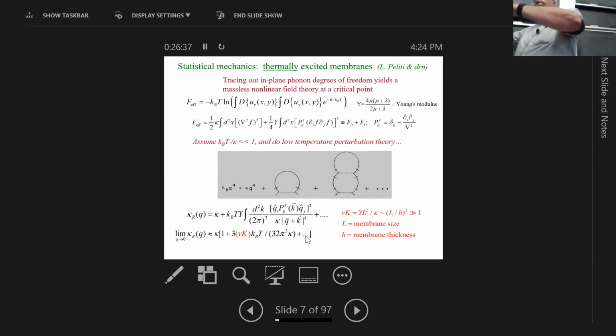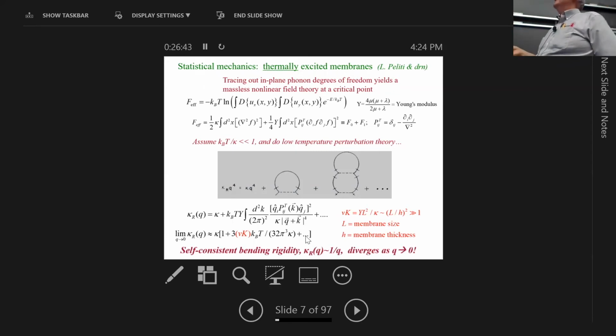And by taking the wave vector close to zero, you're looking at longer and longer wavelength undulations. And what you find is not just a logarithmic singularity, it's a singularity where the bending rigidity goes like 1 over the wave vector. So it says that this elastic constant doesn't have a Q goes to 0 limit. Some of you might know about long time tails. Well, this is long time tails on steroids because you go to longer length scales and these elastic parameters diverge. And strongly, diverge very strongly.